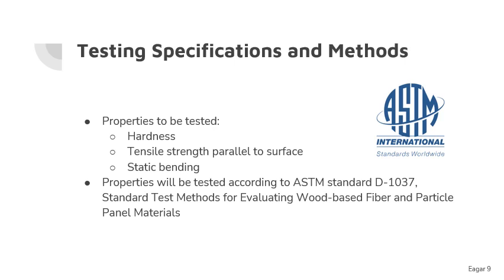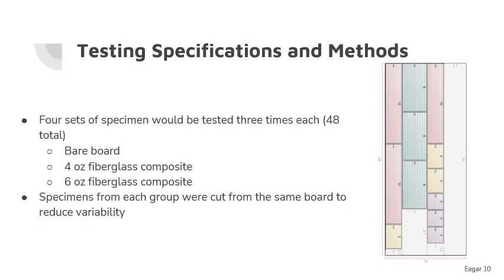So the properties to be tested were planned to be hardness, tensile strength parallel to surface, and static bending. And the properties were tested according to ASTM standard D1037, which is the standard test methods for evaluating wood-based fiber and particle panel materials. Due to equipment availability, we were unable to test hardness, and our specimen sizes needed to be reduced to fit inside of the equipment. 4 sets of specimen were planned to be tested 3 times each.